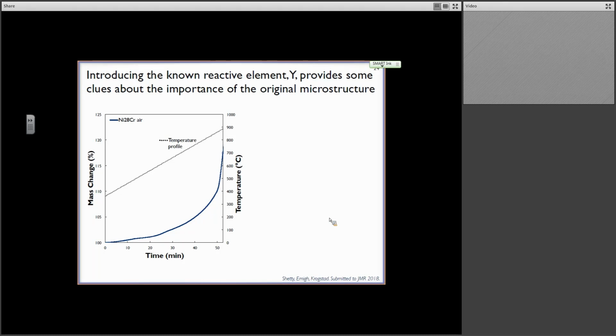Okay. So what we did is we introduced to these same alloys, the nickel, chromium, aluminum system, a known reactive element, which is yttrium. In this introduction, we only introduced about 1% or less of yttrium.